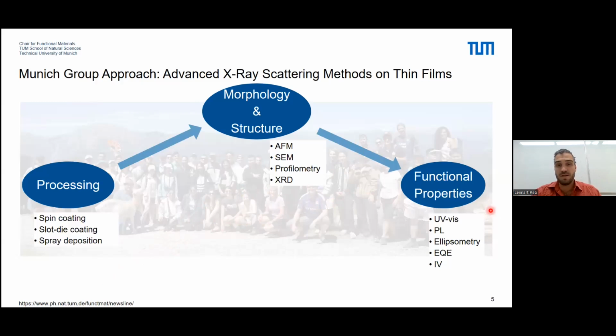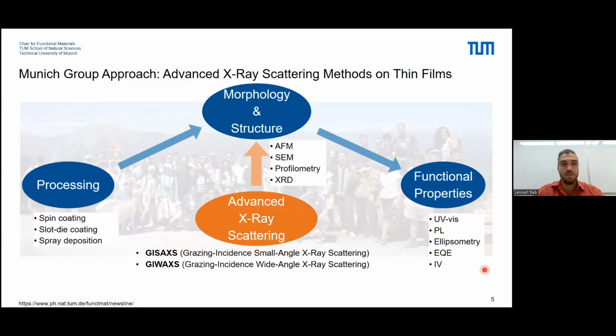Then the functional properties can be investigated in thin film with UV-Vis, PL, and ellipsometry, and of solar cell devices using EQE and IV. So what is now our X-ray scattering? When I'm talking about advanced X-ray scattering, I mean GISAXS, which is grazing incidence small angle X-ray scattering, and the wide angle sister technique, GIWAXS. And these two techniques are the key of our group, because what we can do with this, if we have a brilliant source, is first of all do in situ experiments. And these in situ experiments allow us to shed light on the kinetic evolution of morphology and structure during processing.